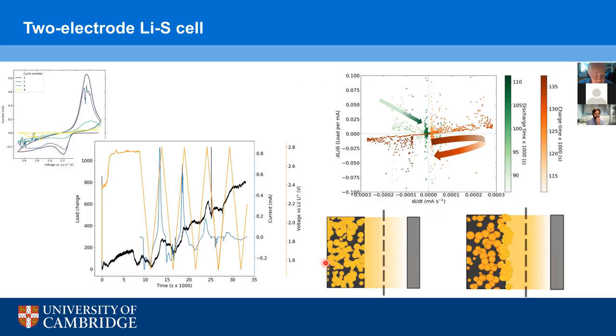Okay. So as a starting point, we looked at a 2-electrode lithium sulfur cell, which is well characterized electrochemically in terms of this composition of electrode. So in the top left, there's the electrochemical profile of the cell, which, if you can imagine that being unraveled, is represented by the blue line in the larger graph below it.